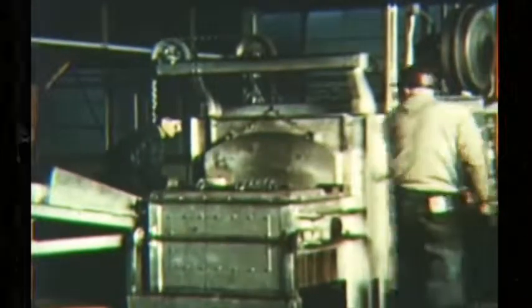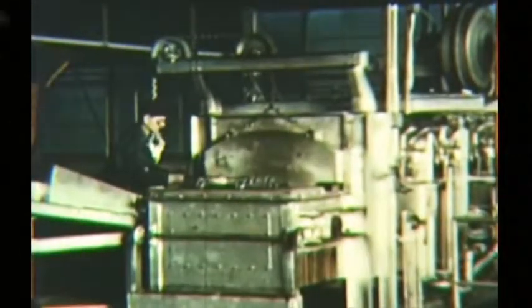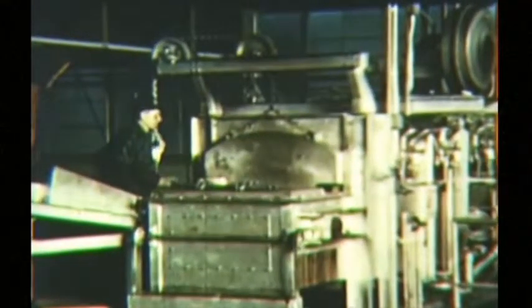This is a typical modern continuous type heat treating setup. The forgings first enter the hardening furnace, where they can be brought to any specified temperature from 1400 to 1900 degrees Fahrenheit. As they fall from the belt at the end of the furnace, they drop into the quenching bath below. This can be whatever water or oil bath is required to obtain the desired properties.